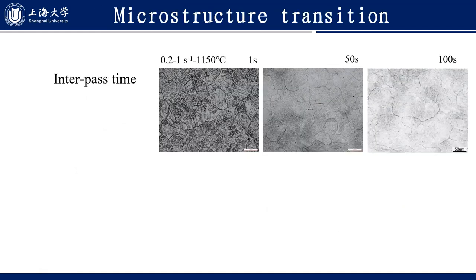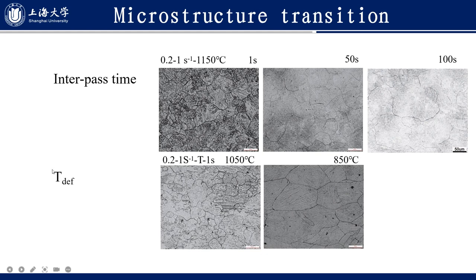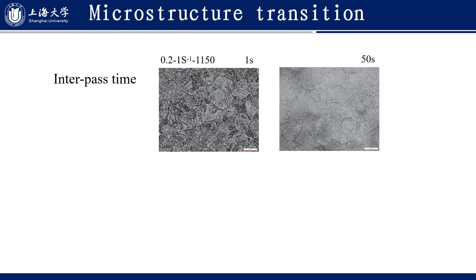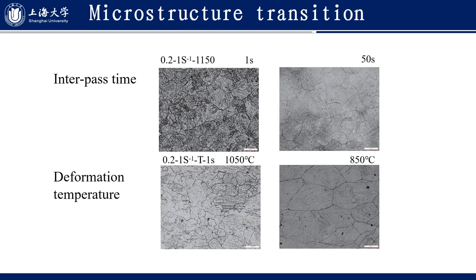The microstructure transition at interpass times of 1 second, 50 seconds, and 100 seconds. We can see the recrystallization behavior. And for different deformation temperatures, say 1050 degrees C and 850 degrees C, the recrystallization fractions are totally different. For different interpass times and deformation temperatures, the steel shows different recrystallization fraction and grain size.